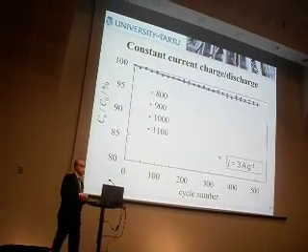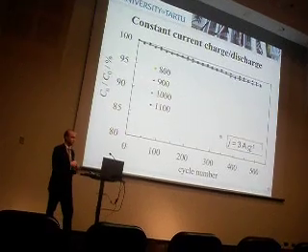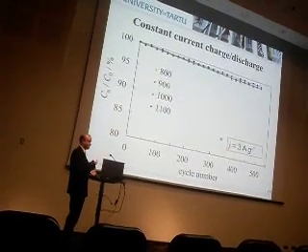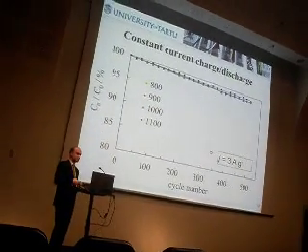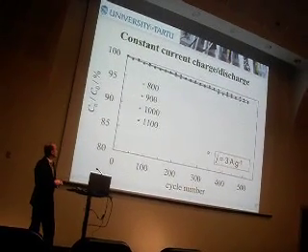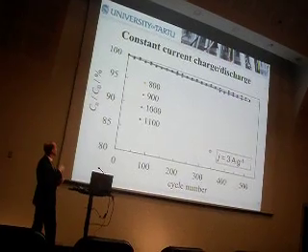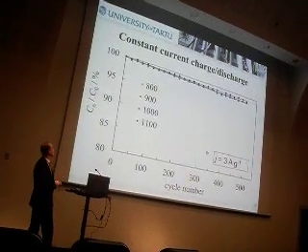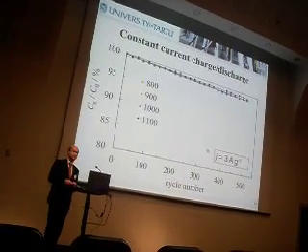And this is the measurement where we cycled it 500 times, and we can see that the capacitance did not drop very much. It stayed around 98 to 99%.